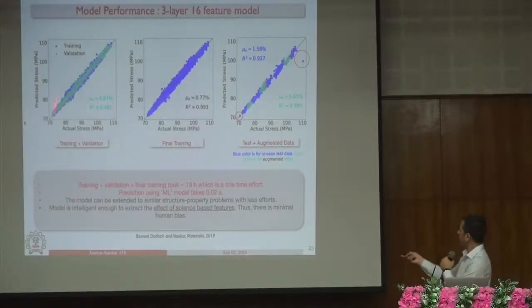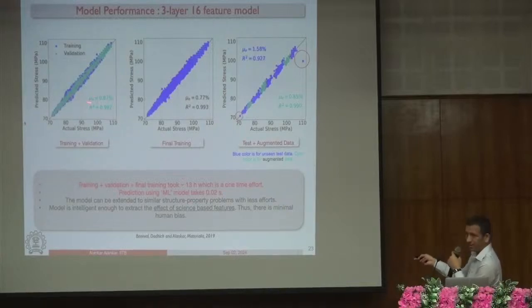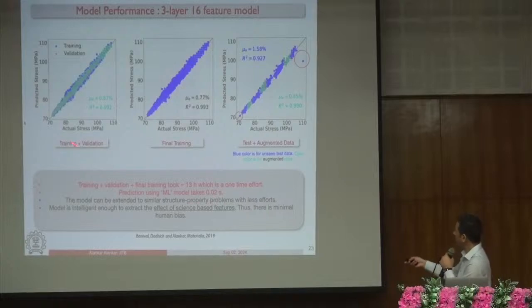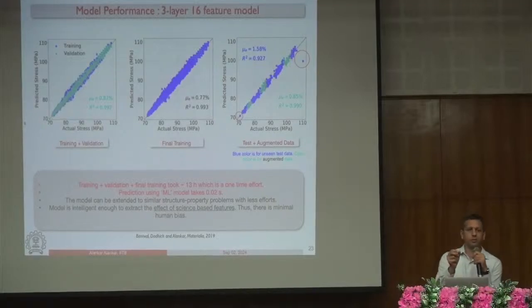All right. So what it shows is that again, you can have a very good correlation between the predicted stress and actual stress. You are able to capture it with a very low amount of error. This is the mean of error, only 0.87%. R2 value is 0.992. And this is training and validation, which is obvious because all the data has been seen by the model. And this is the final training, meaning all the data that was used for training and validation has been shown to the model now. And again, the results are pretty good, right?